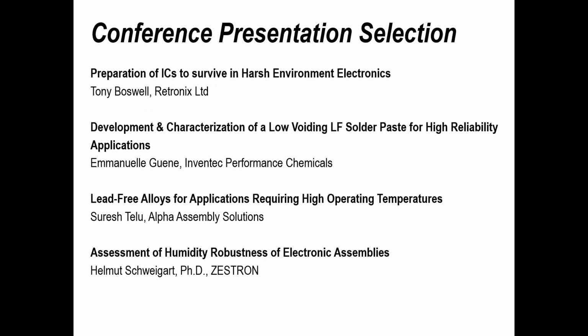Now, voids is something Keith mentioned in his presentation, and voids are always a debate. I tend to find a lot of voiding is related to the design or other aspects. A lot of customers have problems specifically with paste and profiling, and you can do all you can with improving your process, but at some point the paste product needs to change. You will find that certain paste products produce better void performance than others. But because you've got all those variables in between, it's just understanding what is the true cause of void. So I always say to people, find out what the root cause is first of all. Don't always blame the paste and the profile.